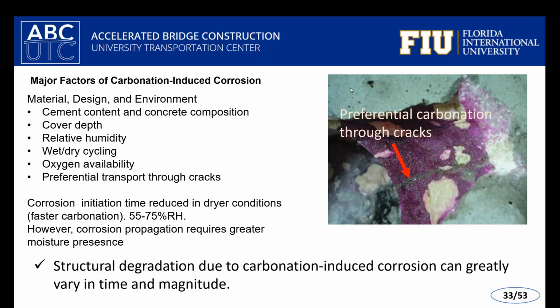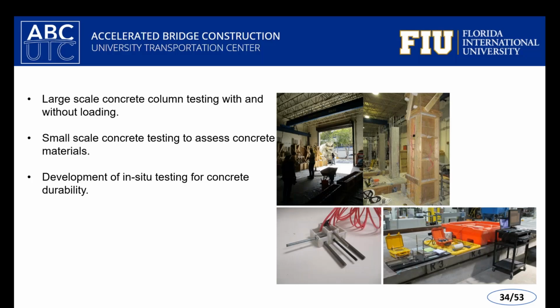It is dependent on the material that you use, the design detail provisions of the rebar placement, the environment, and the cycling of the environmental conditions. Many different things affect this, so often it's very difficult to get a firm grasp on service life. And so, piggybacking off some of the work that Fatima mentioned, especially the second project looking at the retrofit system, at FIU we did some experiments with those very specimens to identify the effect of carbonation, how it can occur, and also with the retrofit.